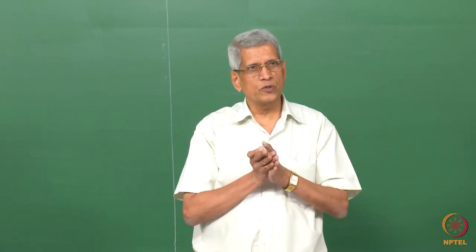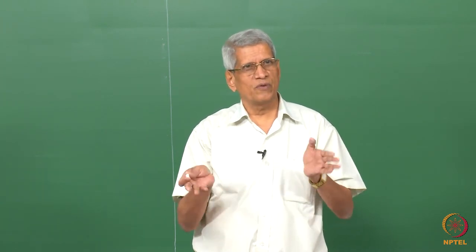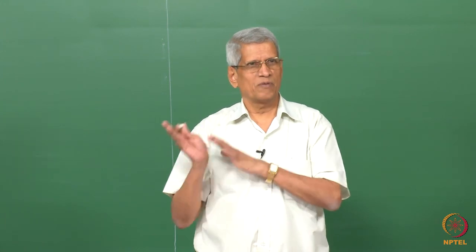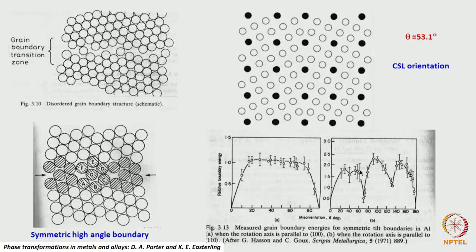What boundary it will choose is the one which generally will have the lowest energy, correct? For various angles of misorientation, we can have cusps like this in the energy. These are also possible. These are all more favored compared to other boundaries with very high energy. These are all what we consider as equilibrium calculation.